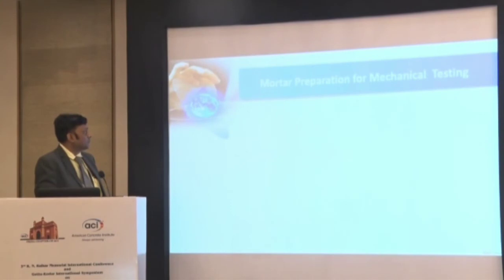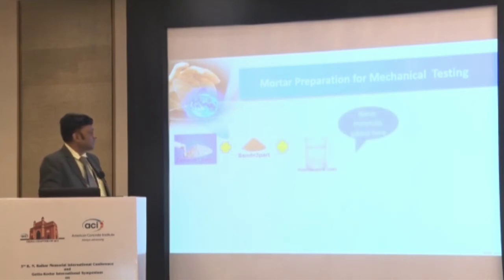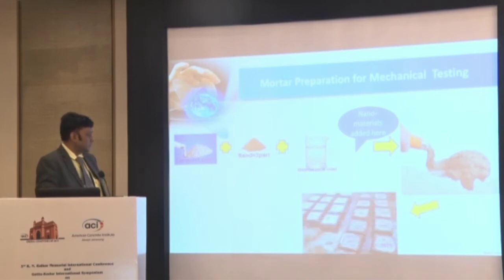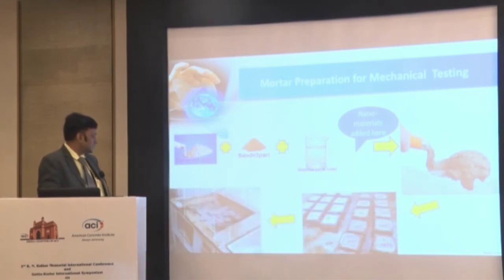For the mortar preparation for mechanical testing, cement one part, I have used sand 3 parts as per IS codes, plus water as per IS codes, and nanomaterials at this time I have added. It cannot be dissolved in water, so I have added in a different fashion. I am going to show you that. We prepared the mortar, we cured it, and we then tested it in the lab.